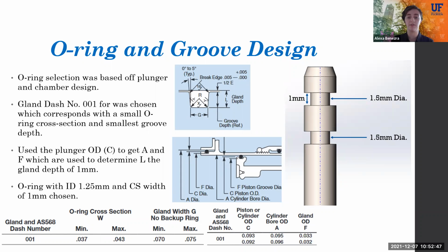And since the Parker O-ring handbook values were smaller than our actual values and moving up in a dash number would be too large, we chose to go with 1 millimeter gland depth and 2 different gland widths of 1 millimeter and 1.5 millimeters for testing. And the 1 millimeter gland width created a seal with no leakage that was verified later in testing. Additionally, we also used 2 O-rings instead of 1 to decrease the friction on the individual O-ring.